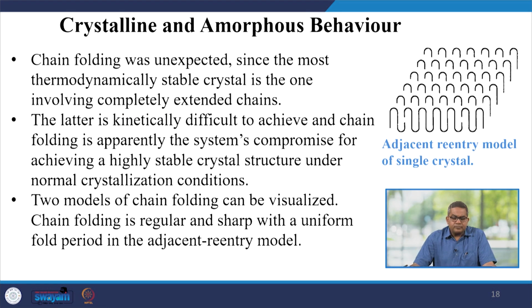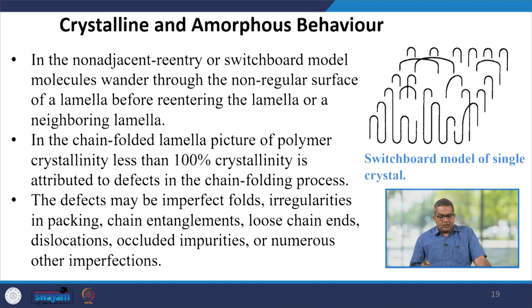The chain folding was unexpected, since the most thermodynamically stable crystals are ones involving completely extended chains. So, kinetically it is difficult to achieve, and chain folding is apparently the system's compromise for achieving a highly stable crystal structure under normal crystallization conditions. Sometimes the non-adjacent re-entry or switchboard model is used, in which the molecules wander through the non-regular surface of a lamella before re-entering the lamella or a neighboring lamella, like here you see this particular aspect.